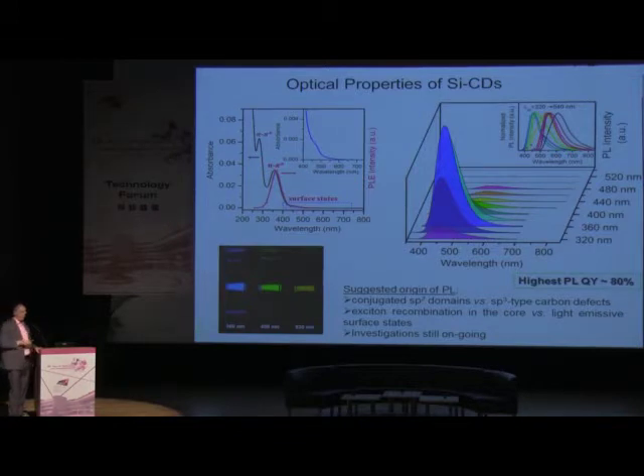They show a number of what we call molecular-like transitions, like pi-pi star, n-pi star, and their emission, as I mentioned, is tunable by the wavelengths of excitation. They emit strongest in the blue range. Green emission is still rather strong, and if we would like to get emission shifted to the yellow part of the spectrum, to the red part of the spectrum, this emission is typically very weak.